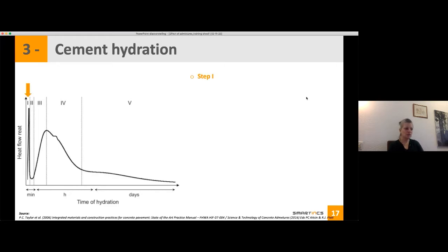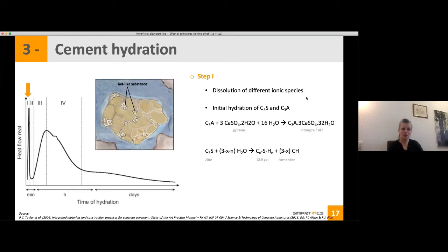And the first one, you see you have a very high and a sharp peak. And this is from the moment when you have your cement, your binder, and your aggregates in contact with water. You have immediate dissolution of different ionic species. And you have an initial hydration of your tricalcium silicate, the C3S, and your C3A. What will happen? If you have your aluminate, it will react with your gypsum, and then you will form ettringite. So this is really fast.